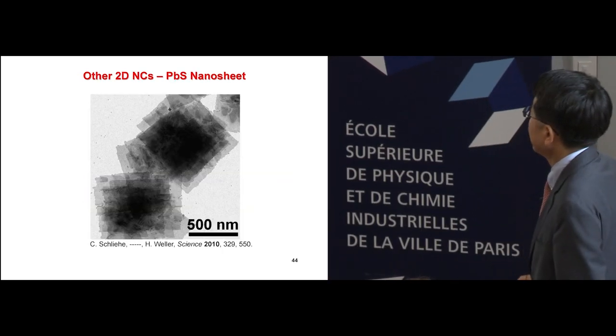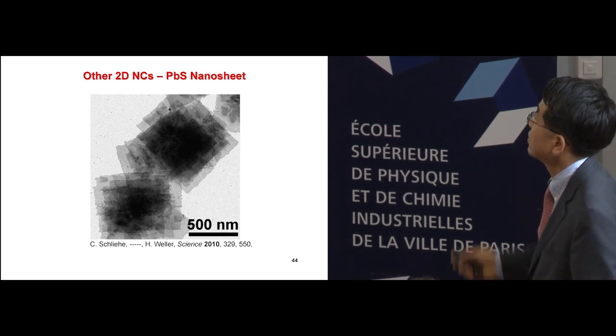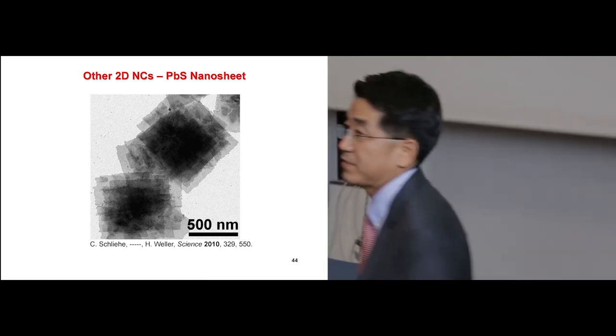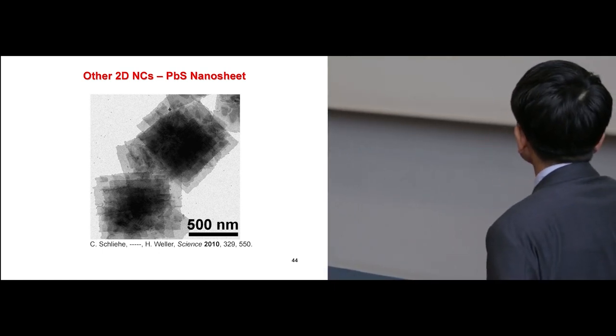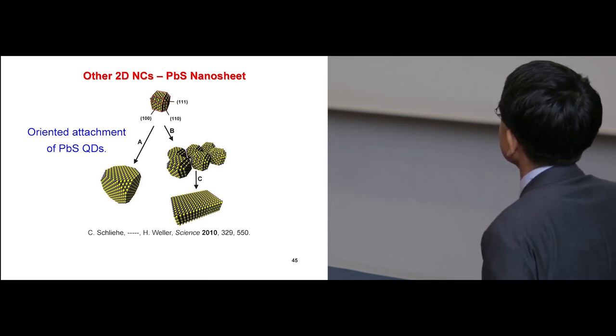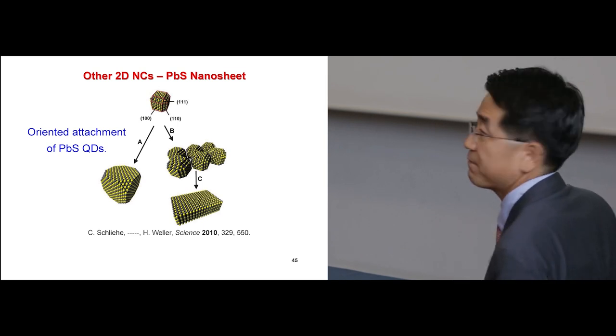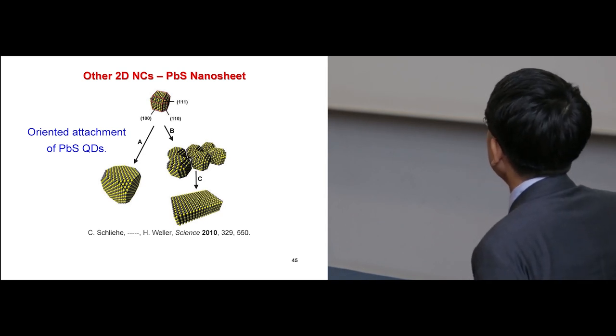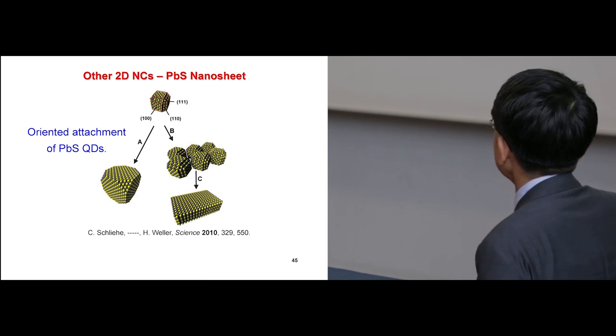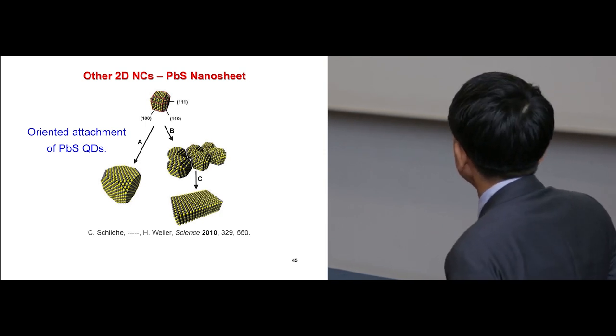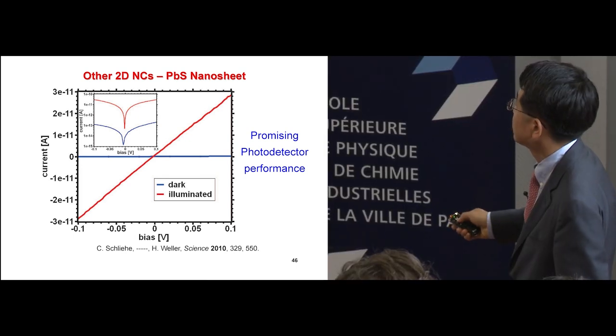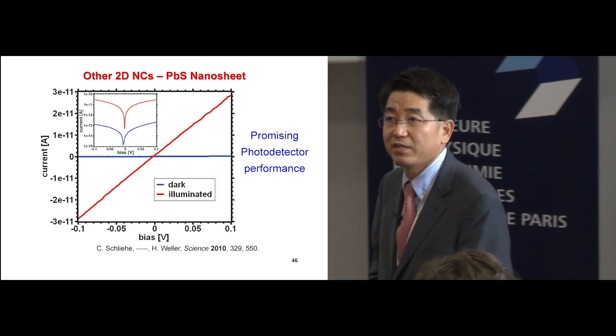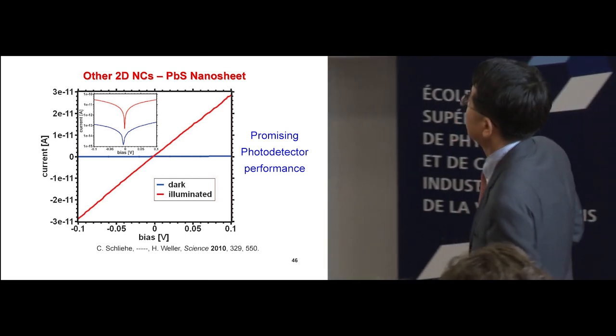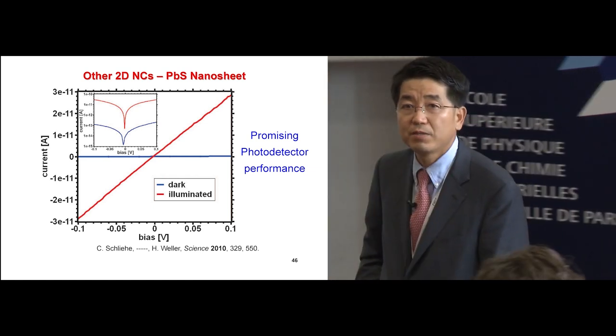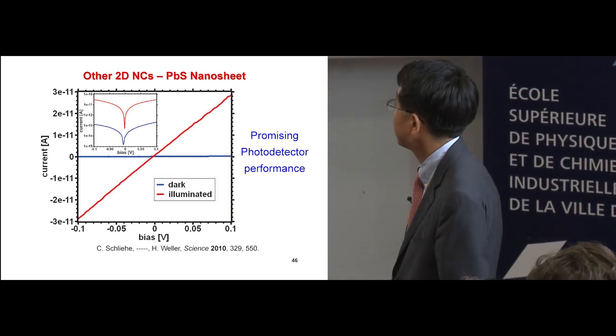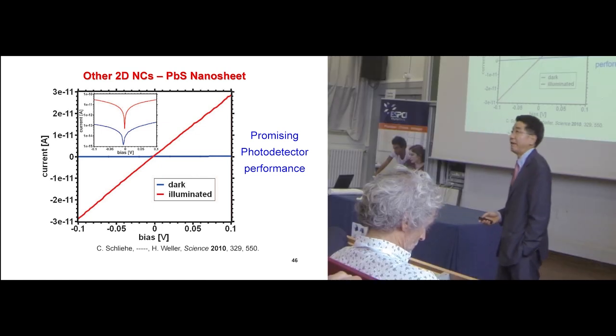Later, Horst Weller's group reported the synthesis of PbS, lead sulfide, nanosheets. They said it is a similar mechanism, oriented attachment, starting from spheres, then cube-like structures, which eventually stack together through oriented attachment to make a plate. That's what he reported in Science. His group also tried some photoconductivity measurements. Not super, but it still shows possible applicability to photodetectors using this PbS nanoplate material.